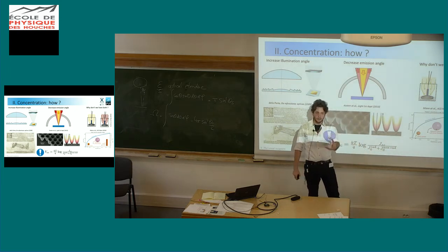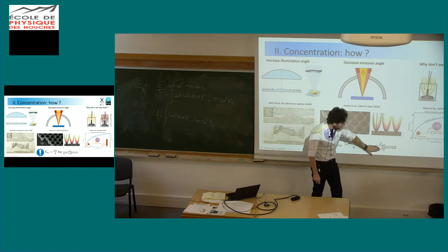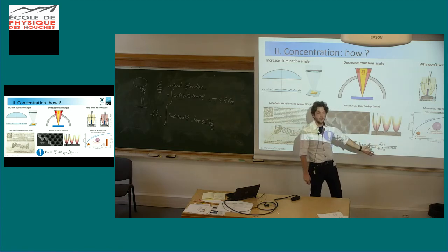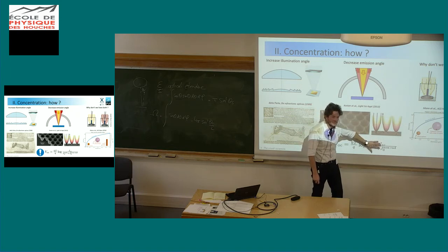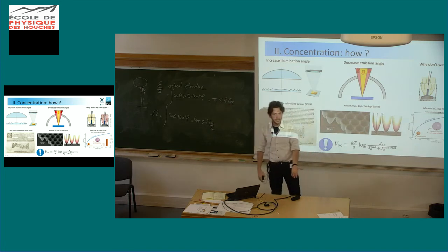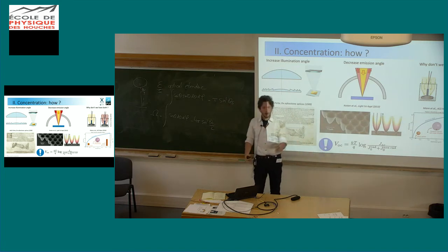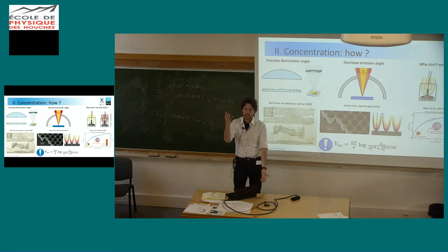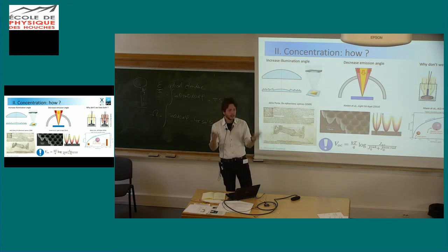So you're making a lot of efforts to reduce this guy, which at the end of the day has almost no influence onto the final voltage. So from a theory perspective, if everything was ideal and you only had radiative losses, decreasing J0 from radiation or increasing JSC from illumination would be equivalent. In real life, of course, it's slightly different. Okay?